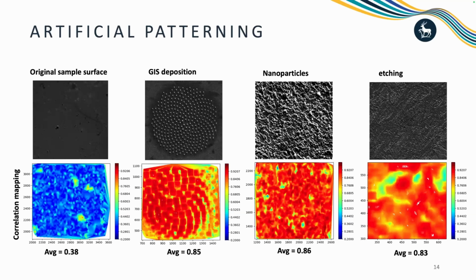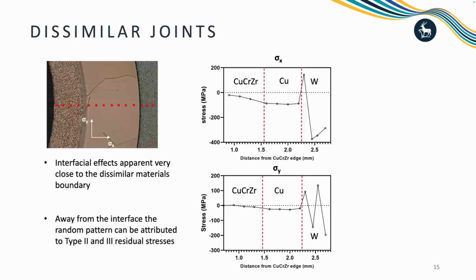Let's see the results of those three methods. The first one is the original surface without any treatment, and we can see the correlation coefficients of each map. For the rest of the three methods, they gave quite similar correlation quality, and the nanoparticles slightly win this comparison. And then here are the plasma focused ion beam DIC results of the residual stress. We can see the residual stress distribution. The interval between two measurements is about 200 micrometers, and we can see the distribution along this line scan. We can find tensile residual stress at the tungsten copper interface, balanced by compressive stress at the two other sides.